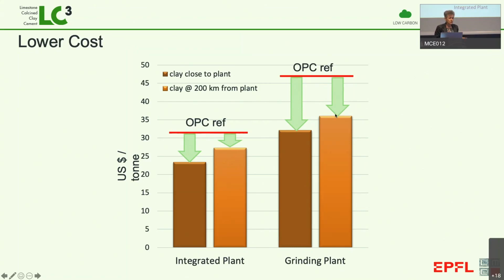Now, this is the situation in many parts of Africa because Africa doesn't have many deposits of limestone. And that means many countries, in fact, are importing cement clinker and then grinding it locally to produce cement. They haven't got much limestone, but they have got lots of clay. And if they produce calcined clay locally, they can produce very big savings compared to the reference Portland cement.